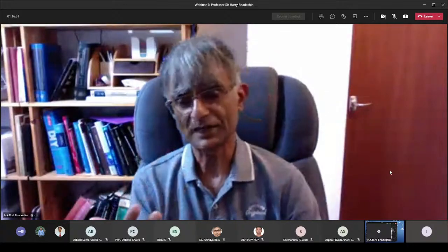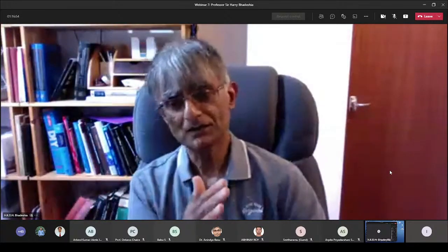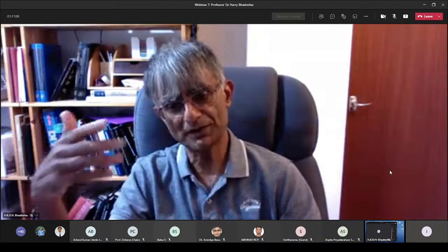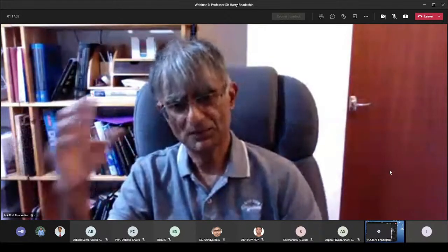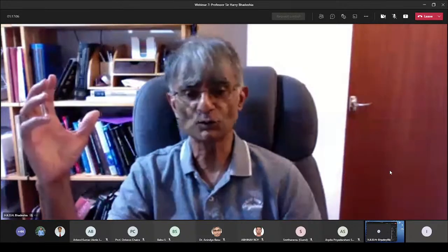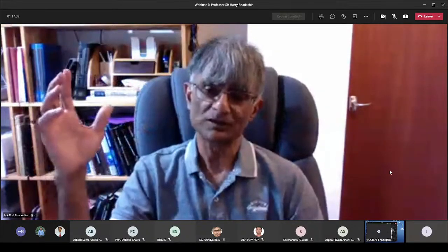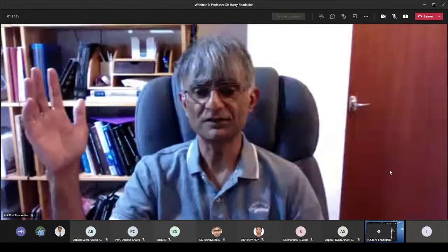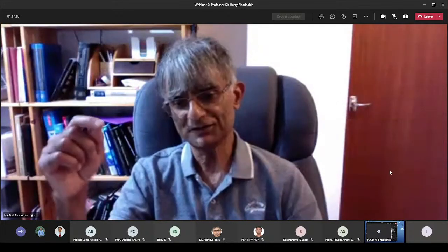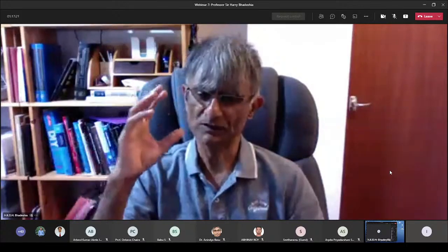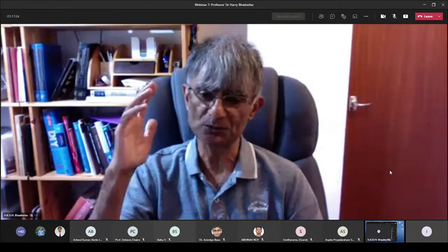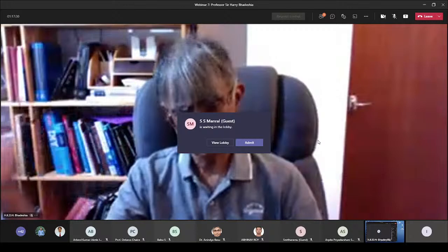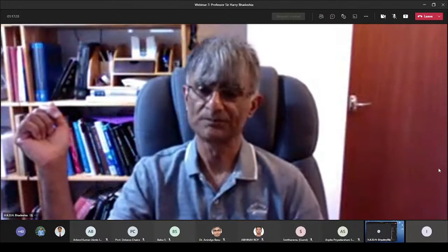But if you compare with aluminium addition, aluminium performs better than nickel in shifting the T0 curve to a higher concentration because aluminium is a ferrite stabilizer. But it's a rough way of thinking because, for example, chromium does not stabilize austenite. You can add sufficient chromium so the austenite completely disappears. But at the same time, it reduces the martensite start temperature. So the best way to think about it is in terms of the difference in free energy between austenite and ferrite. If that difference can be increased, then the T0 curve will move to a higher carbon concentration.